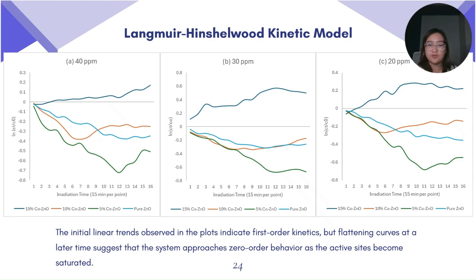The experiment also observed that all photocatalysts, except the 15% co-ZnO, would degrade properly in the beginning of the runs, but would later produce intermediates or byproducts. Zinc oxide produces the least number of byproducts, judging by the behavior of the lines in this figure. It plateaus in contrast to the 5% and 10% co-ZnOs, where they observably create a positive slope at different time points. It may have also formed byproducts that are stable and resistant to further degradation.